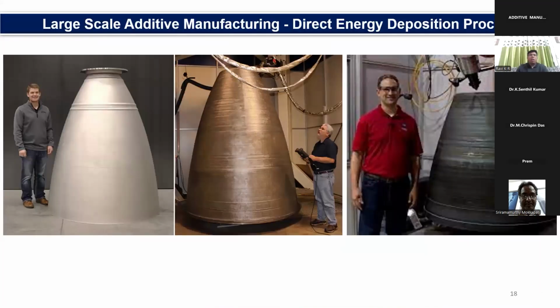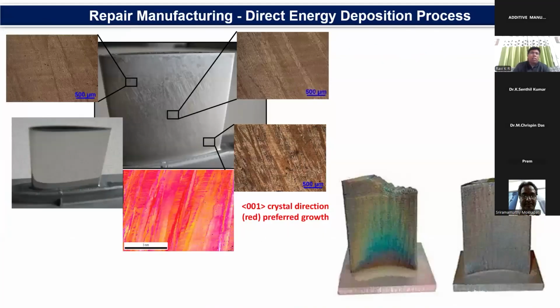As I told you, in direct energy deposition, one can make very big parts. That's what you can see here. In addition to that, it is very useful for repair manufacturing, especially turbine blades, where you need to have proper control over the crystallographic orientation, which cannot be achieved by normal welding technique. Repair manufacturing is one of the major advantages of the direct energy deposition process.